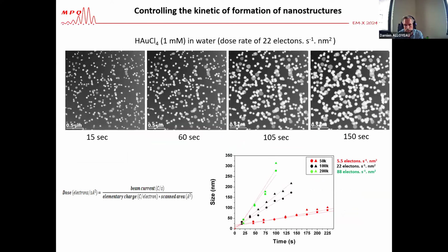Here, an example from my group. You have a gold precursor that is irradiated in water. You observe the growth of nanoparticles. Here you see what's going on when you are in STEM mode. When you increase the magnification in STEM, you decrease the scanned area, so you increase the dose rate, and you see that when you increase the magnification, you increase the growth speed.